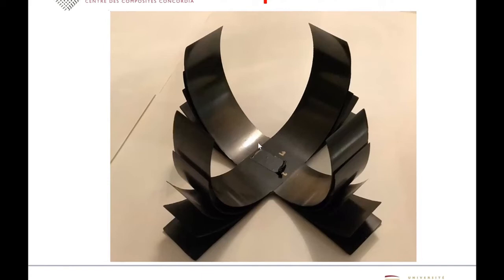So again, this technique is unique in the sense that you cannot use the conventional method of manufacturing composite to do this, because the conventional way that people make composite structures is that they have to make a mold. In this case, if you make a mold, you can only make a mold of one particular configuration. You cannot make a mold of several configurations. So the mold can give you only maybe one shape, but not all of the five different kinds of petals like this. So you can only do this using the technique of 4D printing of composite.